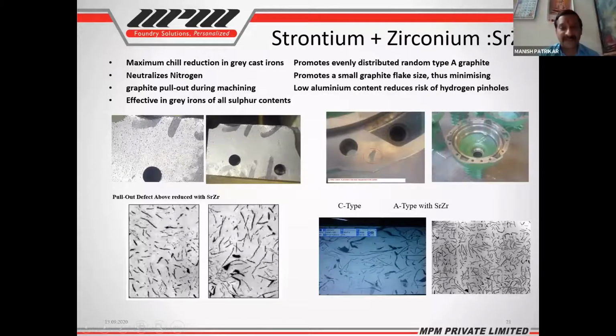This is the RA housing where earlier they were having C-type defect in the microstructure, which has improved with the help of strontium and zirconium. This is also a similar defect, where they have C-type and open grain structure after machining, as you can see on the left. But while using strontium zirconium inoculant, we were able to eliminate this defect.